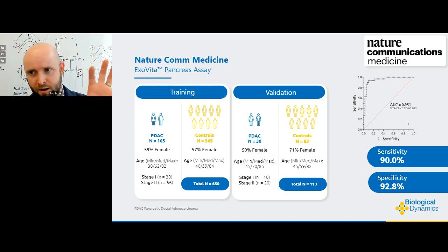And so we trained with that set, applied the algorithm to an independent validation data set with 113 samples, 10 stage 1 and 20 stage 2. And again, the AUC that we're producing with that assay, our Exovita pancreas assay, is about 0.95 with 90-plus percent sensitivity and specificity, respectively. So this is really class-leading performance in this space. We're really excited about it.